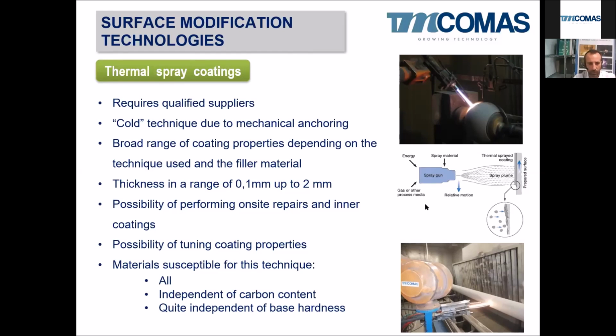Okay, no. So you can modify the porosity of the coatings, for example, by modifying the parameters. You can use a zirconium oxide coating in a very porous way as a thermal barrier coating, or you can use it very dense, with low porosity, to protect some paths for molten metal. So the same material, zirconium oxide, can have two different coating properties for two very different thermal applications.